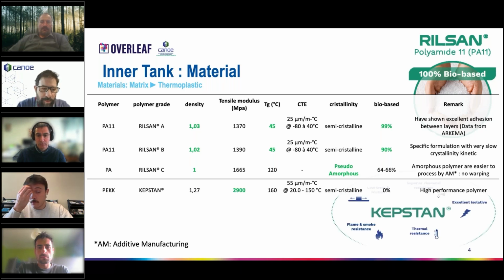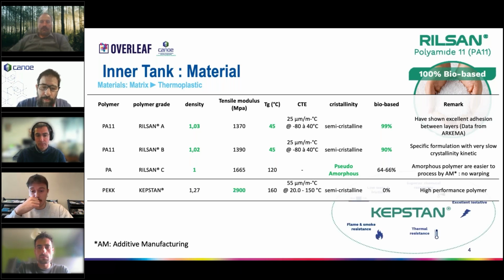Then we tried another candidate, definitely different from polyamide. This one is a high temperature, high performance polymer from the Kepstan family. It's a polyether ketone, something similar to PEEK. These materials have higher performance in terms of mechanical performance, but also in thermal performance, because the glass transition is pretty high, something close to 160 degrees. When you compare to polyamide, which starts from about 50 degrees up to 120 degrees for the Rilsan Clear.